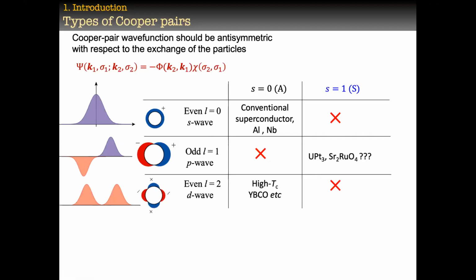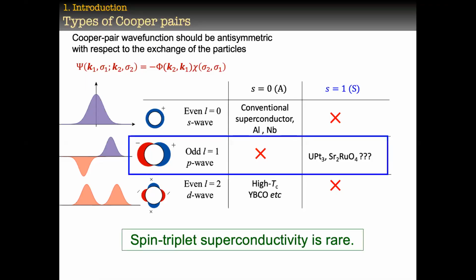And now let's go to the higher order D wave. It is again the spin singlet, because it has S equal to 0, the orbital part is symmetric, and we do not have spin triplet type here, and the high temperature superconductors are D wave and spin singlet. So it also shows that this spin triplet superconductivity is rare in nature, and these are quite tough materials, and I will show you later why it is difficult to get spin triplet superconductivity in nature. And now, can we do something with these Cooper pairs?